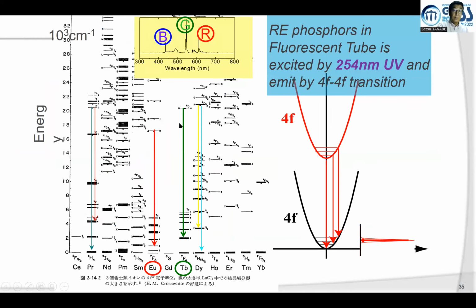Many of the luminescences are composed of f-f transitions, which are shielded by 5s and 5p electrons. Many visible luminescences, from terbium green and europium 3+, have sharp features. This is not rare. This is actually a mercury line of a fluorescent tube. The 254 nanometer UV light of a fluorescent tube can efficiently excite the phosphor materials developed for this purpose.